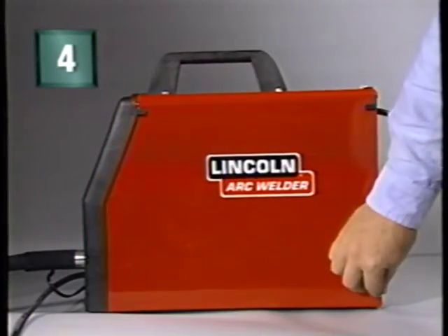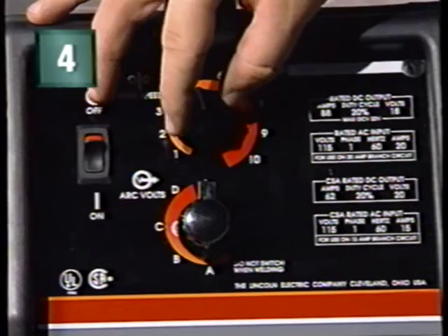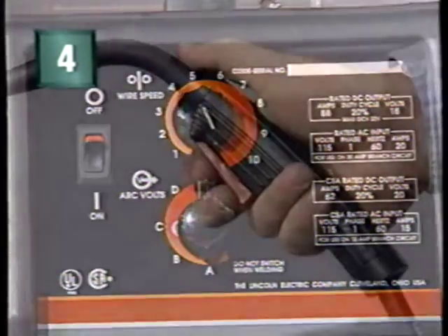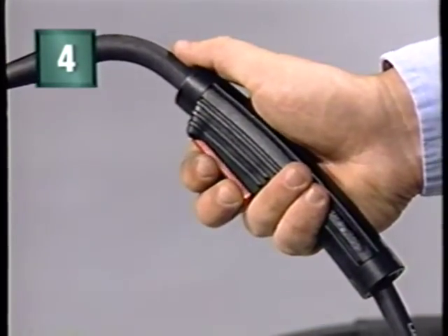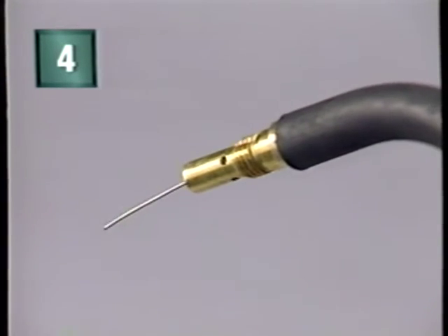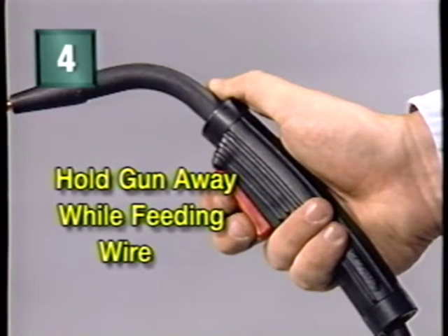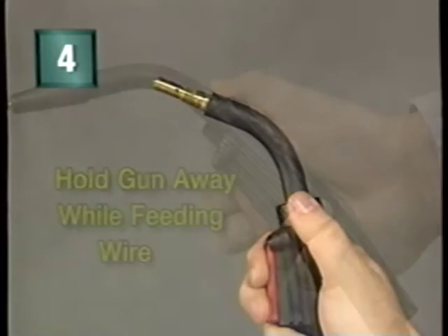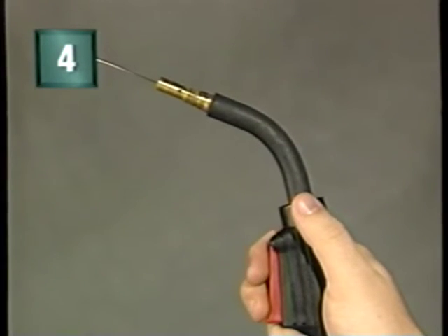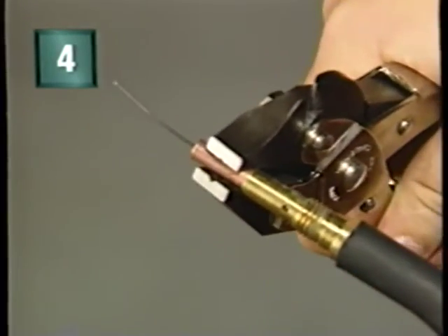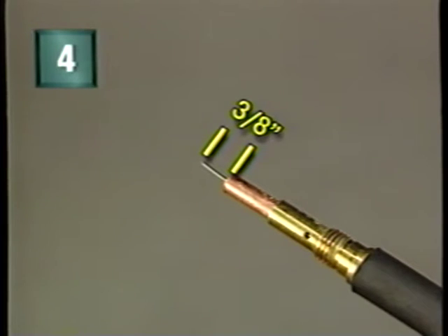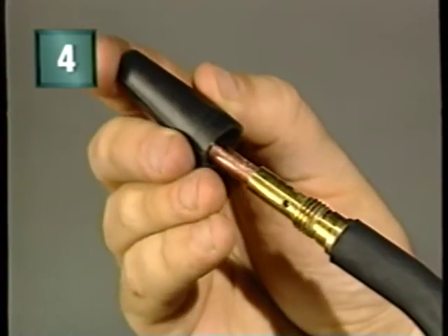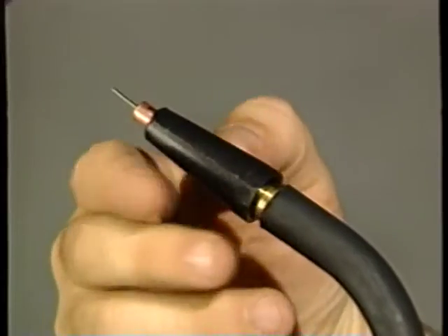Close up the unit, plug it in, turn it on, and turn up the wire speed control. After straightening the cable, squeeze the gun trigger and feed the wire through the cable. Hold the gun away from yourself and others while feeding wire. When the wire is exposed, stop feeding wire and replace the contact tip tightly. Then cut off the wire about 3/8 inch from the end of the tip. Also keep in mind that the 3/8 inch stickout is important while welding. The setup for Innershield welding is now complete.